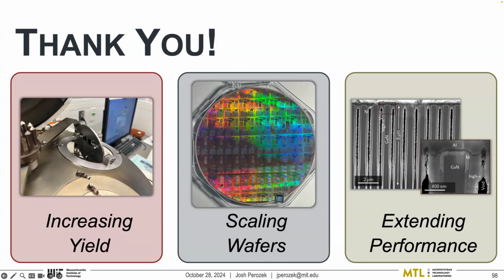Right. So the big problem with this is that we do need that TMAH wet etch to make the sidewalls very smooth, and that only happens along a particular crystal plane. So you want the M plane exposed along the sidewall there. So as you change the angle of that, it takes away your ability to make a smooth sidewall. And as these trenches get very deep, the etch gets very messy, and you really need to be able to clean it up with that wet etch. So what would actually probably have to happen is for structural support, just kind of cut out a portion of the diode and don't have fins there just to keep them all connected, and just do that every so often periodically to keep it kind of standing up straight.